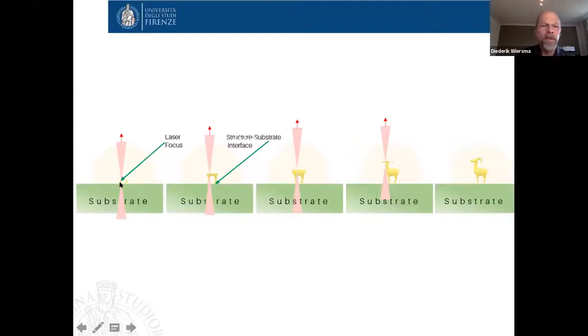So you have this mixture and you make it such that the laser light triggers a catalyst so that the chemical reaction starts, and the chemical reaction will take place at the focus point of the laser. And then the laser is scanned through this droplet. The light actually comes from the bottom, and where you have the focus, you create the polymer network. This way, you can build up something which has any kind of complicated shape, right?